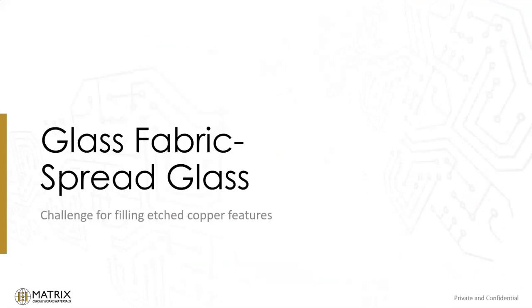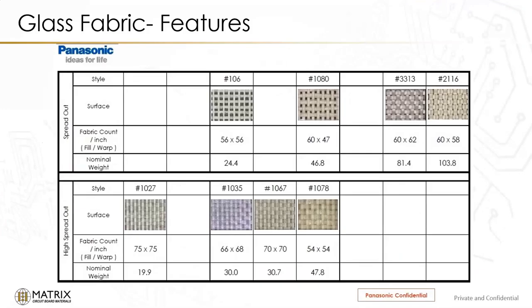And how that would influence that. So if we just look at all the spread glass, we're seeing the 106 in the old days that were used as the thin glass. It has a lot of gaps. The 1080 in this case is spread, but it's not spread enough because of the limitation on the counts in the X and the Y direction. There's just not enough to spread it out to make it a high spread material. The 3313s and 2116s are very heavy glasses, and they just can't be spread anymore. They run out of real estate.